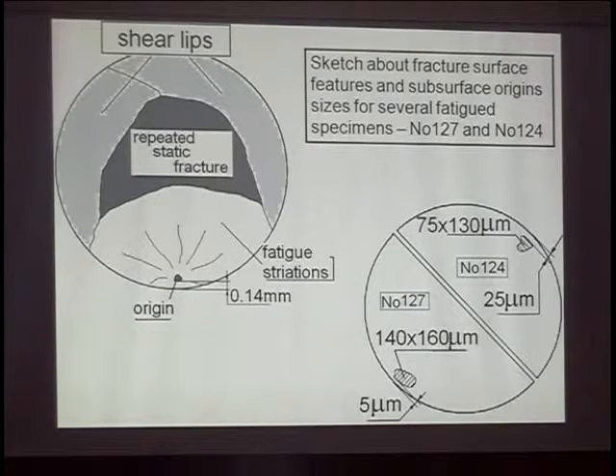First of all, I would like to summarize the results of the investigation. Always, if there is a dramatic change in the bifurcation area from one manner to another, independently of whether the specimen is notched or smooth, there exists a first facet with different size because of the difference in external stress level used to test the material, but the same manner of material cracking, independently of stress level or stress ratio, and independently of the tempering procedure or surface hardening procedure.